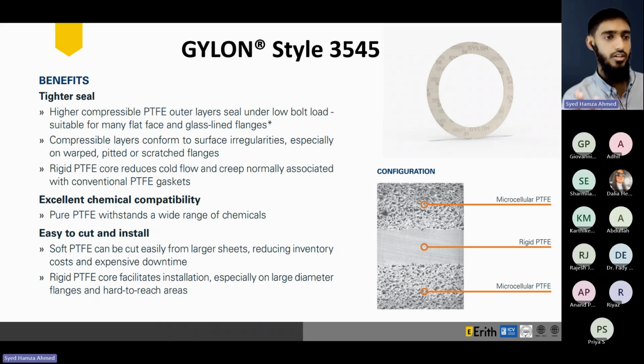Basically, the glass line flanges are being used in severe chemical services, right? And the gasket needs to conform to those standards of chemical service. And since the style 3545 is made out of pure PTFE, we can withstand a wide range of chemicals. And apart from that, the added advantage of using this style of Gylon is that the soft PTFE can be easily cut out from larger sheets, reducing the inventory costs and expensive downtimes, as well as allowing for field cutting of these gaskets.